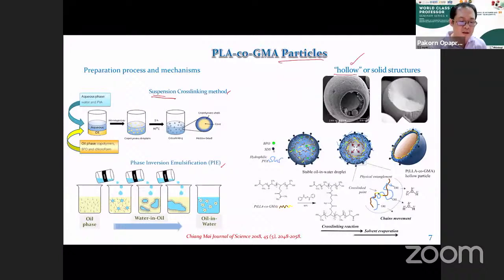So this is called suspension crosslink technique, and the other one is phase inversion emulsification. By using these different techniques, we can make this copolymer into nanoparticles with different structure. One can give us solid particles, and the other technique, PIE here, gives us a hollow structure, with void inside and a shell made from this copolymer.